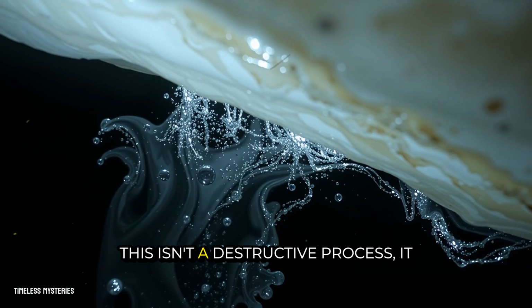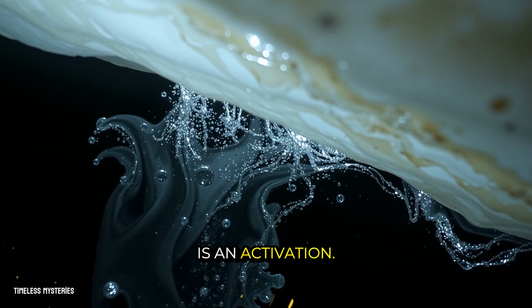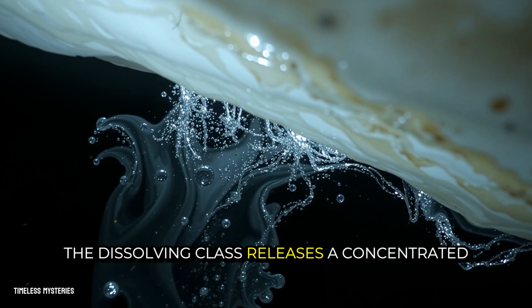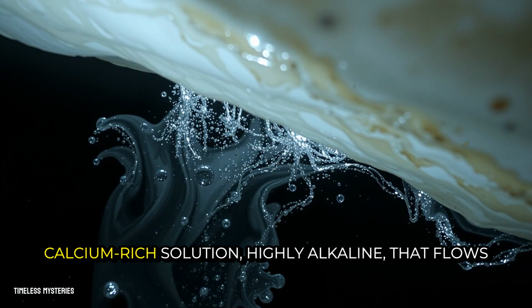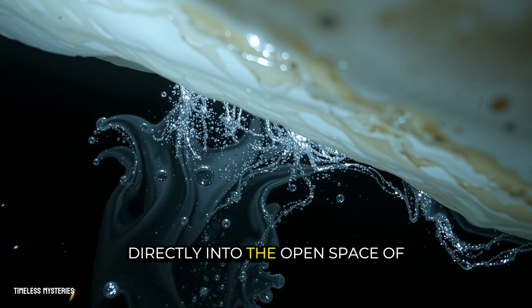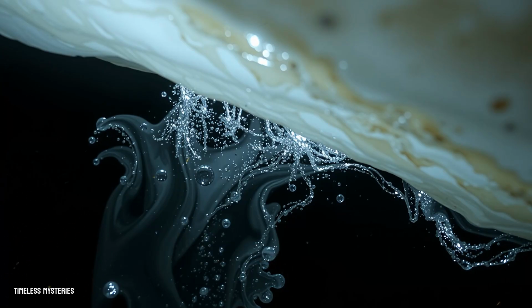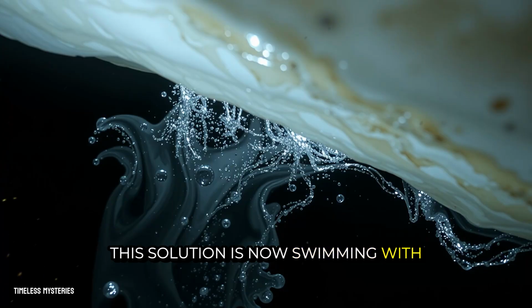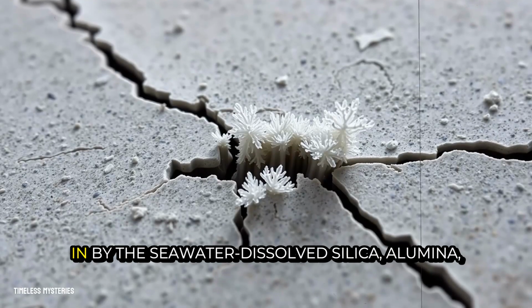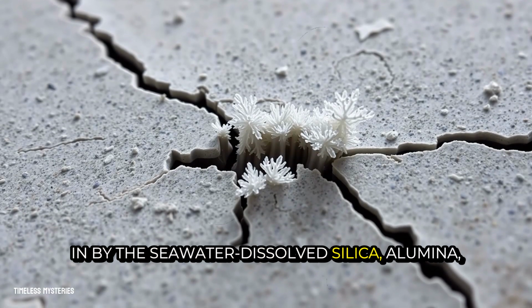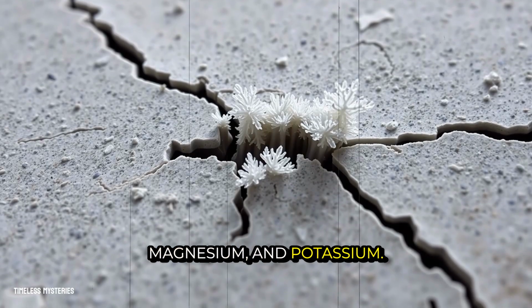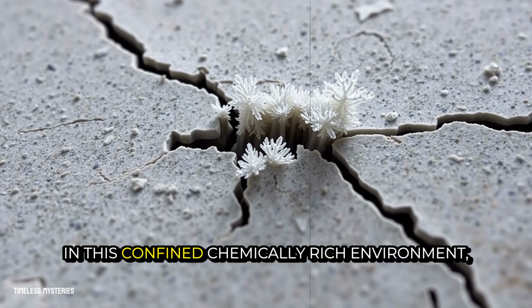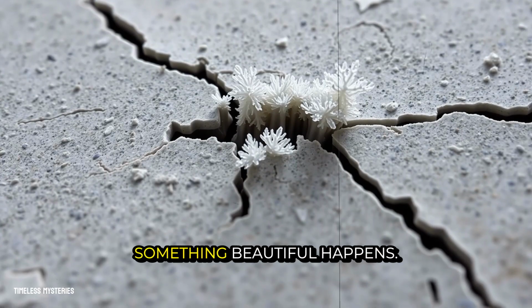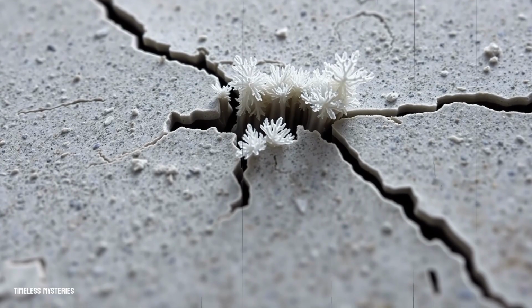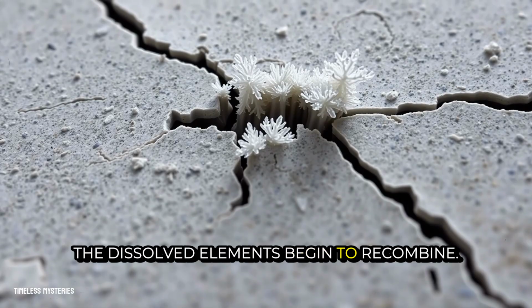This isn't a destructive process, it is an activation. The dissolving clast releases a concentrated, calcium-rich solution, highly alkaline, that flows directly into the open space of the fracture. This solution is now swimming with the very ions that were carried in by the seawater: dissolved silica, alumina, magnesium, and potassium. In this confined, chemically rich environment, something beautiful happens. The dissolved elements begin to recombine.